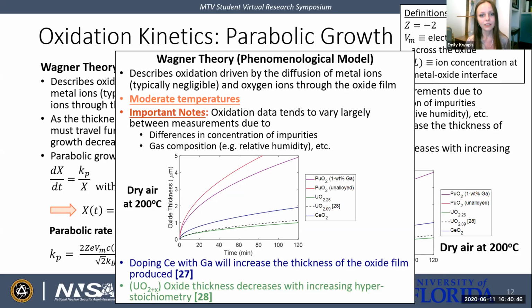And gas composition plays a large role in these disagreements between different published papers. If there's water vapor present in the atmosphere, that leads to enhanced oxidation kinetics and will increase the thickness of the oxide film. So the diffusion coefficients I use for plutonium here may not be in dry air, quote unquote dry air, where there was actually water vapor present. So this could easily be half of the thickness that I got, depending on the diffusion coefficients I used. And that's just what I had to work with.